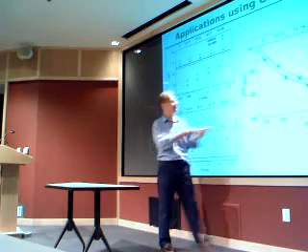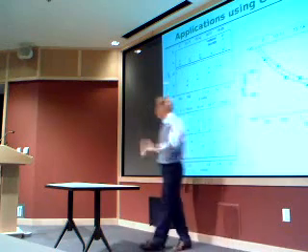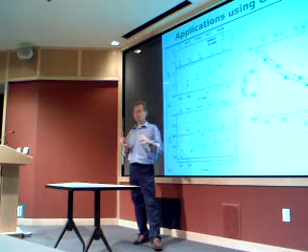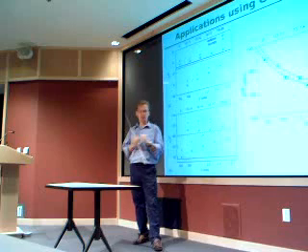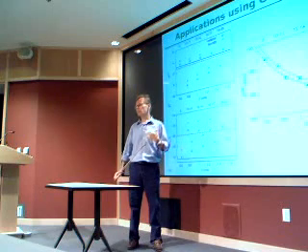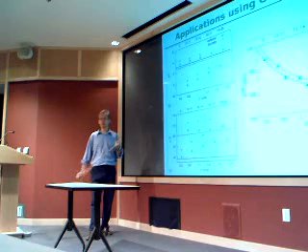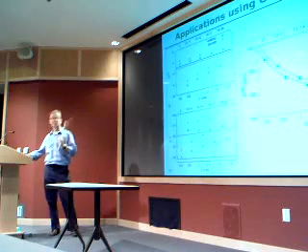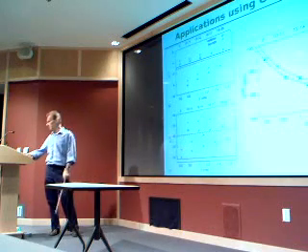And this is now the chemical shift as a function of the radius. So it's difficult for the experimentalists to compare with these values, because when you produce carbon nanotubes, you get nanotubes which, first of all, have all different kinds of radii, and second, some of them are metallic. These are only calculated for semiconductor nanotubes. So you have a full range of values that you would get. The experimental signal is very marginal. They would use these curves to interpret the radius from the chemical shift experiments.